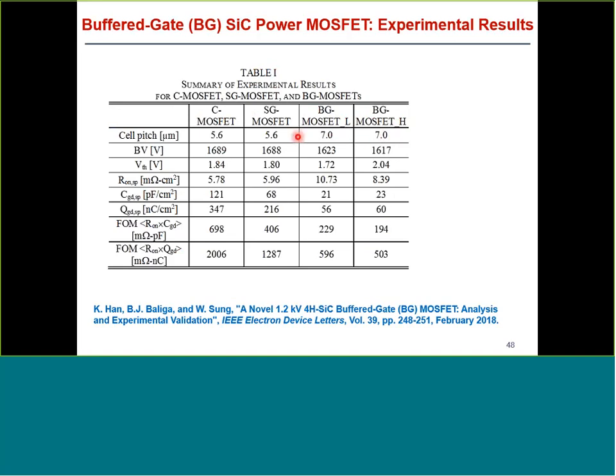In both of these devices, cell pitches are bigger than the conventional SG MOSFETs because of the way the structure is designed. The breakdown voltages obtained are comparable. The threshold voltage is also very close, but because of the larger cell pitch and additional resistances, we do have higher RDS(on) for the BG MOSFET. However, there is a huge reduction in the capacitance, as you can see from these values, and a big improvement in QGD. So this produces a net significant enhancement in the figures of merit. So for the RC figure of merit, we see an improvement of 3.6x, and for the RQ figure of merit, we see an improvement of 4x.